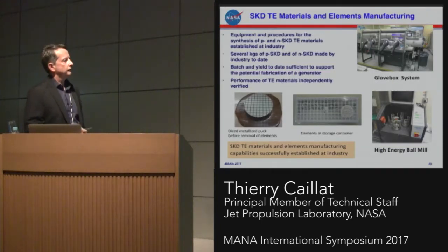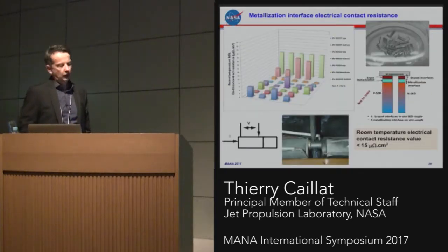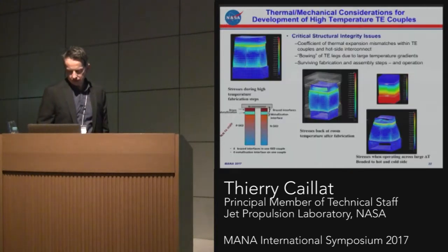So far with industry, it's been able to basically make the materials, make what we call those metallized pucks, which are actually the skutterudites that are metallized prior to couple bonding, and making them into p-n couples. One of the things we want to really achieve is low contact resistance between that metallization of the skutterudites and the interconnect here. Typically the goal is 15 microohm centimeter square.